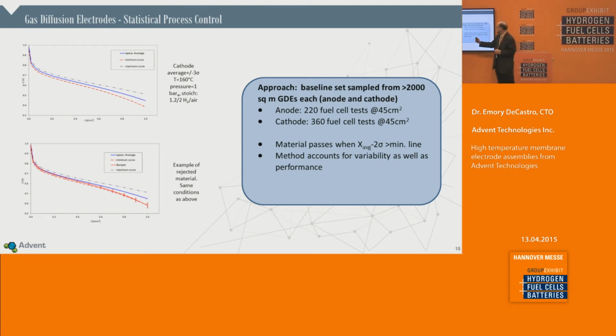Then when a new batch is made, what we do is we do not compare average to average, but we compare the variation of the manufactured batch to the variation of the unknown batch, and compare the average minus 2 sigma to see if that is above our 3 sigma line from the manufactured batch. And in fact, what I'm showing you here is a rebatch or a rejected batch because the variation was a little bit too high. And by doing that, you can be assured of not releasing any bad batches to the MEA manufacturing line, which downstream means that when our customers assemble their stacks, they're assured that 100% of the MEAs are working when they assemble that stack.